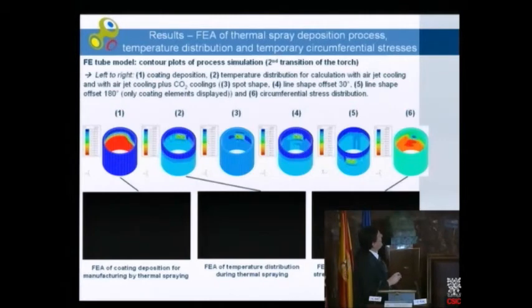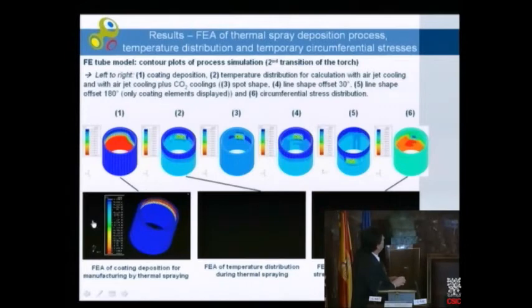So, now the results of this finite element analysis and simulation for the thermal spray process of ceramics on light metals. And we may start left-hand side in the case of just the coating deposition. That means here we show the mass transfer. Oh, great. The piece is under rotation. Here it is shown with a fixed piece, but you may easily imagine, and step by step we change in the finite element mesh, we change the first set of meshes on the surface to the material properties, no more of the substrate, but to that of the coating. So now it is finished.